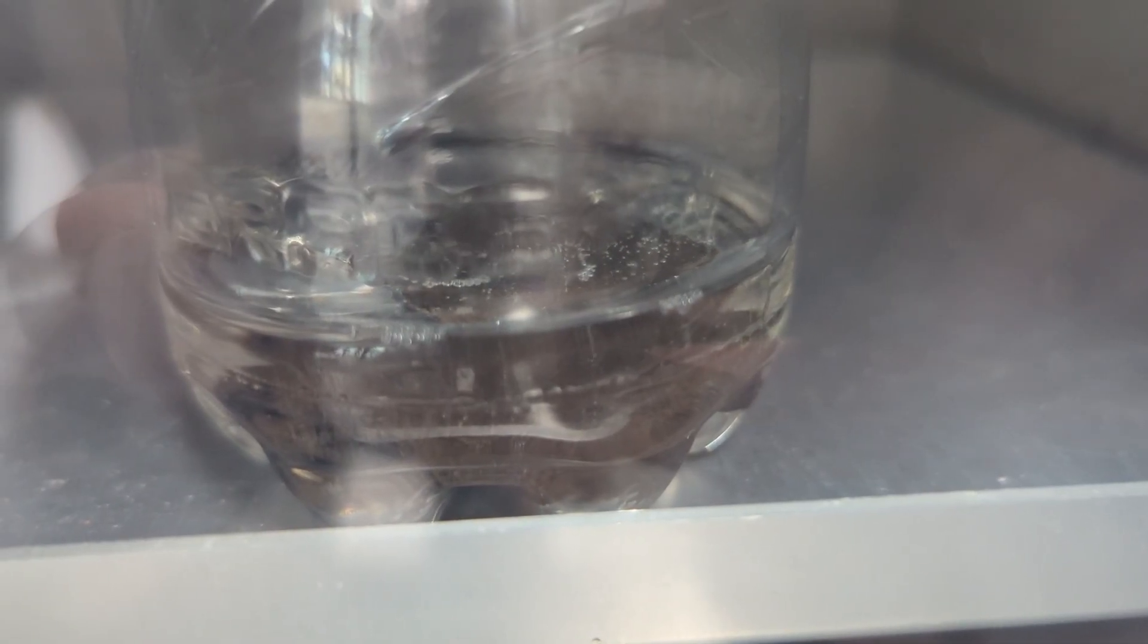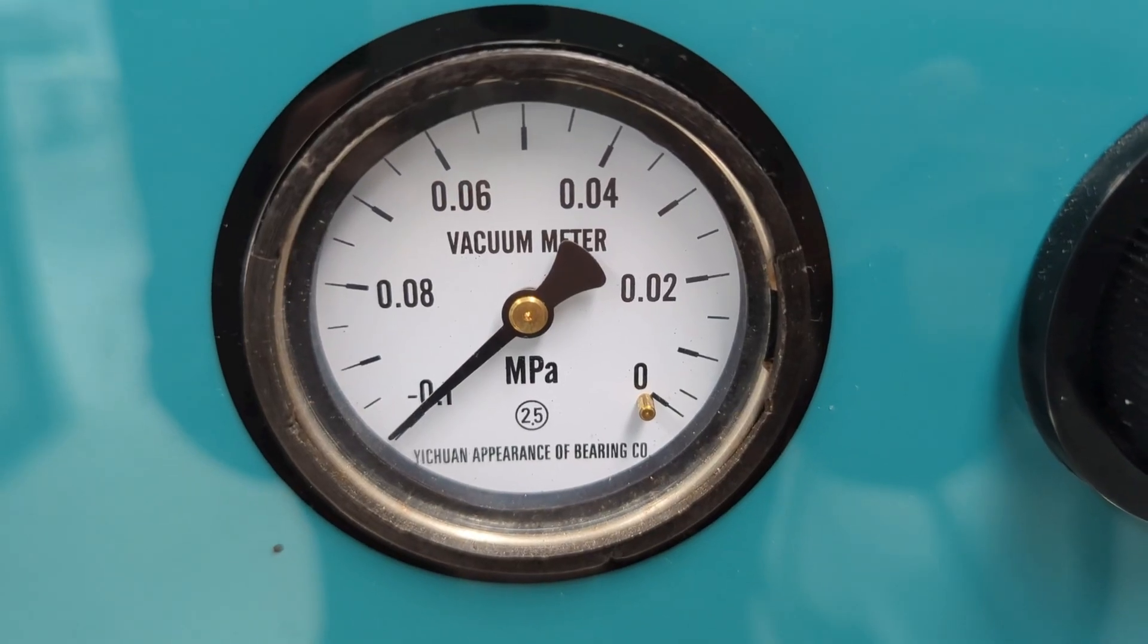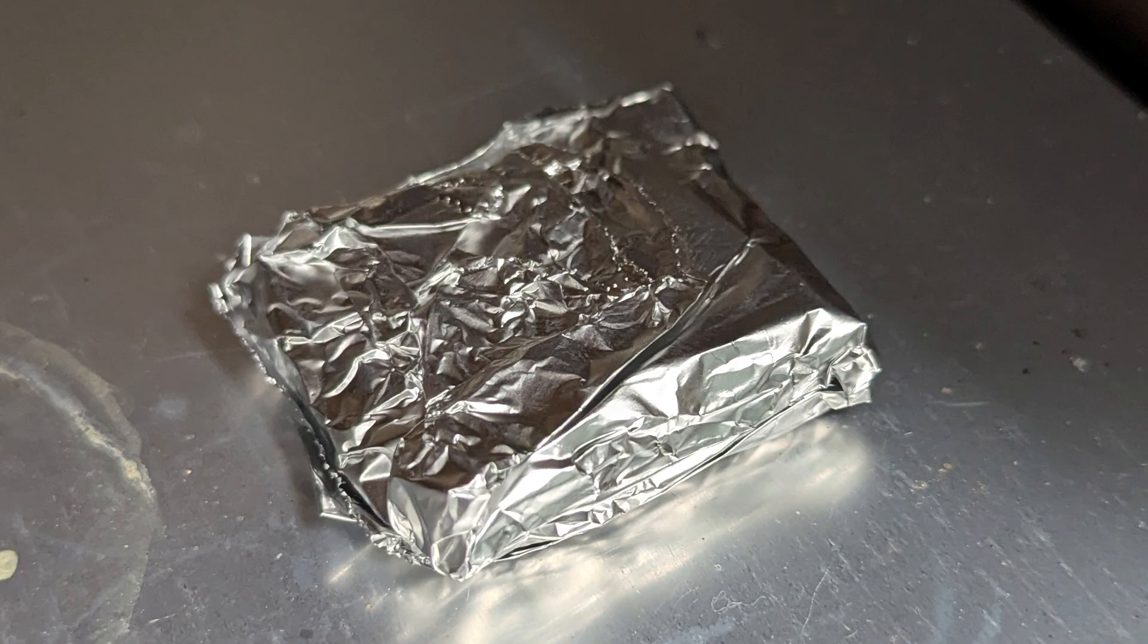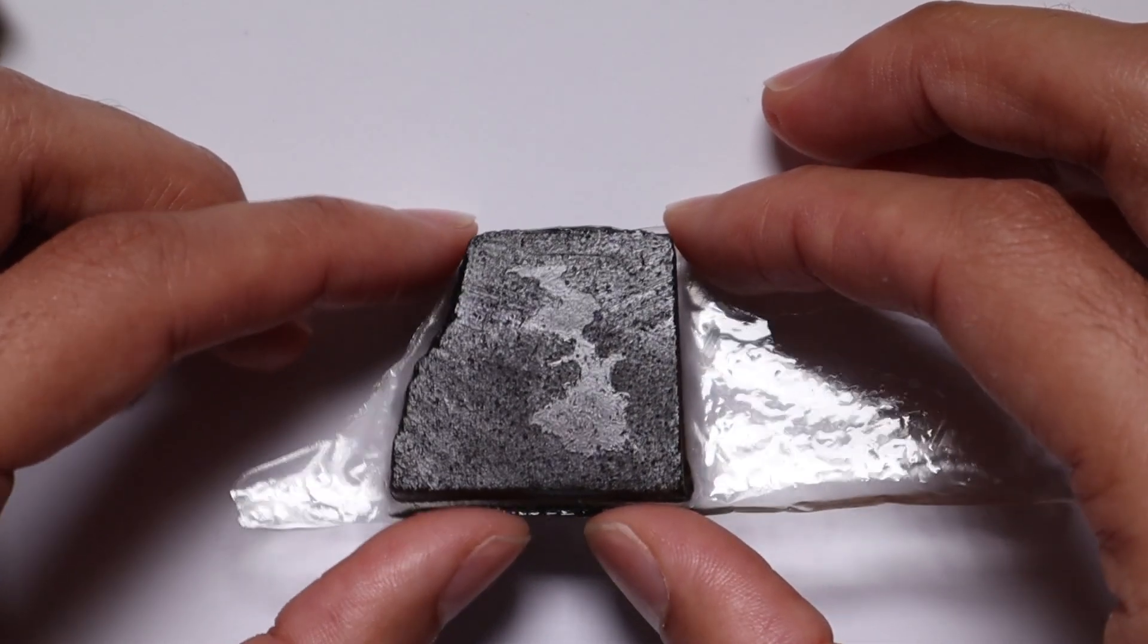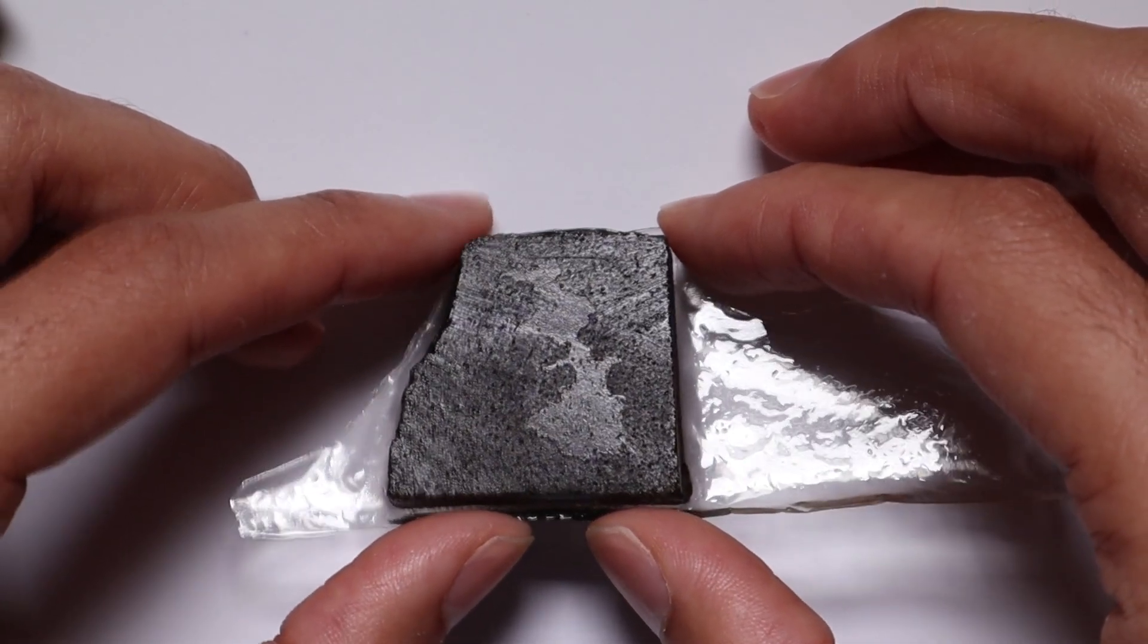This material is super porous. The more porous the material you have the more it's going to take to get in there. But the good news is if you're seeing that incredible amount of bubbling for an hour plus, you know it's getting in there. So once you've got it in there, much like when you're cooking opal, you're just going to take it out. Try not to let it drain too much. Chuck it straight on a piece of foil, just aluminium foil and wrap it up really tightly. And then you want to chuck it into the oven.